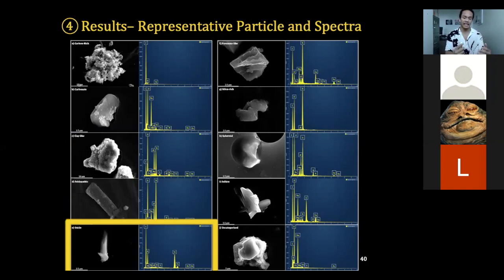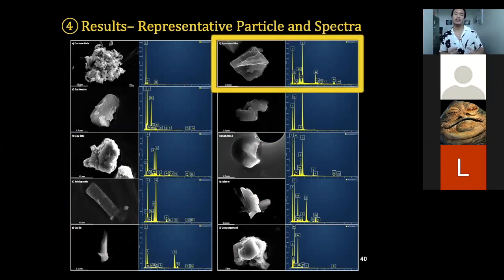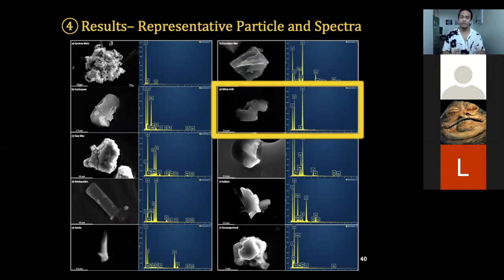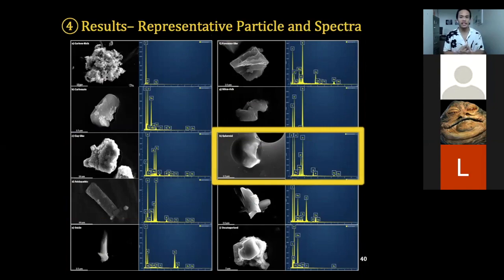So this is an example of a titanium oxide, but we were also able to find iron oxides. The pyroxene-like particles tend to have a blocky morphology, and for the spectra, we look for spectra that have oxygen, magnesium, aluminum, silicon, calcium, and sometimes iron. For the silica-rich particles, they are more angular in morphology, and then they tend to have a strong silicon peak compared to everything else, but sometimes they have other peaks as well, such as this one. The spheroid particles were indistinguishable based on the spectra alone, but if they have a sphere shape, then we lump them into a spheroid category.